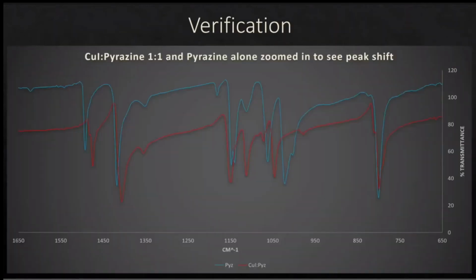And then, of course, we had to verify our results. And so we first turned to FTIR analysis because that's what we had around in the lab. And we found something, once again, very interesting. So the blue line, this is pyrazine by itself. And down below in red, this is the pyrazine when it's bound to copper iodide. And you see that the peaks seem to be just slightly red shifted in the copper iodide and pyrazine. Well, FTIR shows us the relative strength of the bond. And so that showed us that the strength of the bond was lessened whenever the copper iodide bound to the pyrazine. And this is specifically looking in the fingerprint region. So this is influencing carbon-hydrogen bonding primarily.